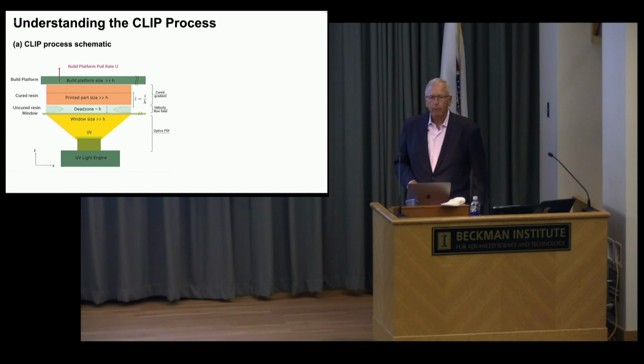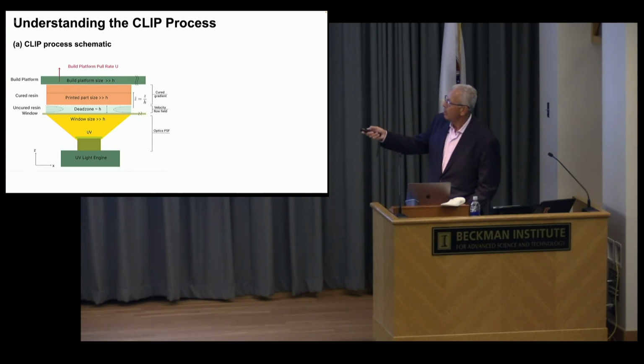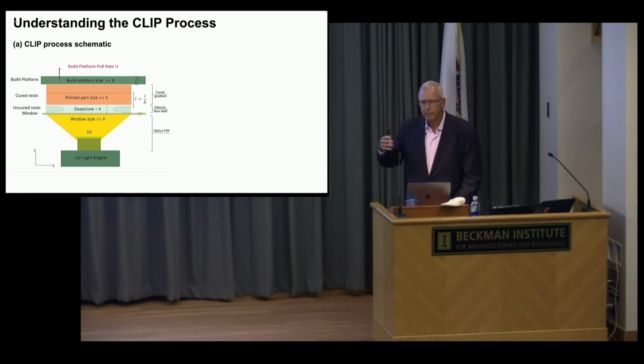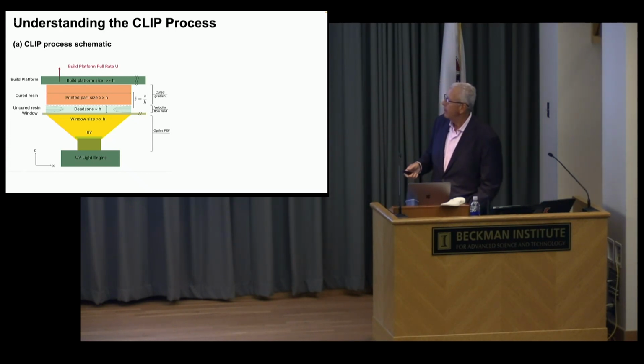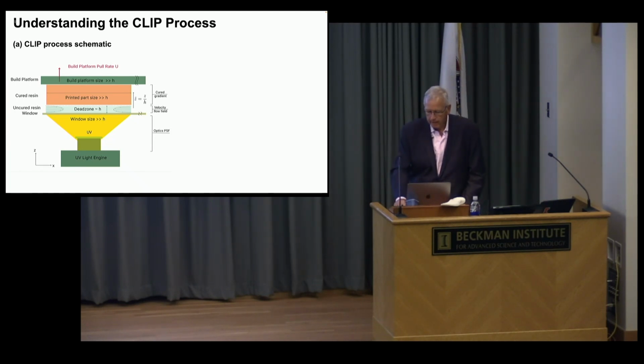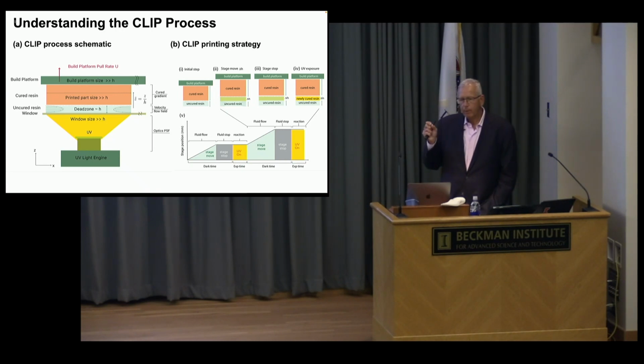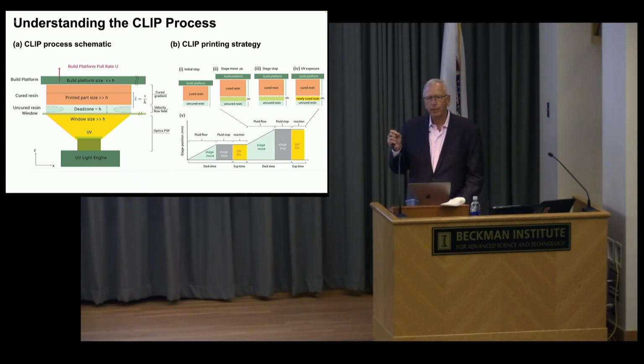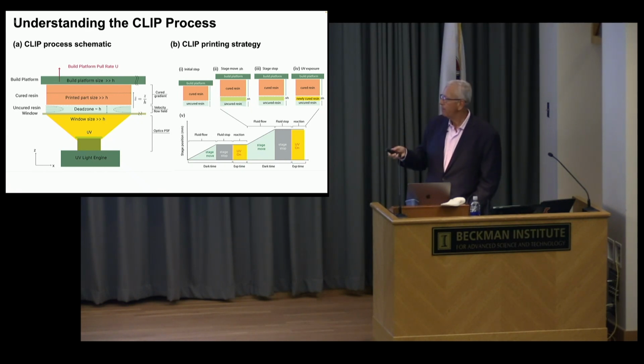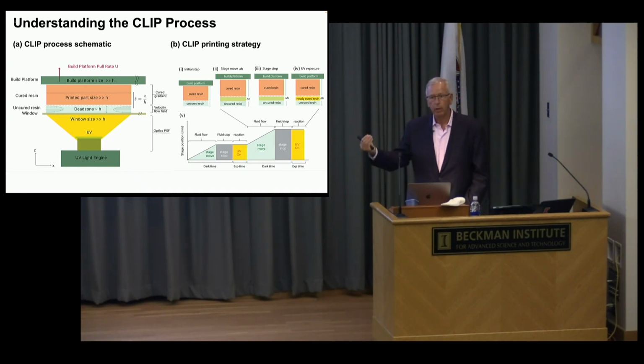And we've mapped this out in great detail. It took a lot of studies, and we're constantly adding to our understanding. But we have a liquid flow into this dead zone. You can have non-Newtonian and Newtonian fluids, depending on what kind of monomer systems you're using. We have a velocity flow field into that gap. We have complete, exquisite control of all the mechanical operations of the printer as a function of time, and the light and everything. So this is an axis of time. This is stage position. We have the printer platform at a certain stage height. We move it at a certain rate with a certain jerk, in whatever way we want to control it.